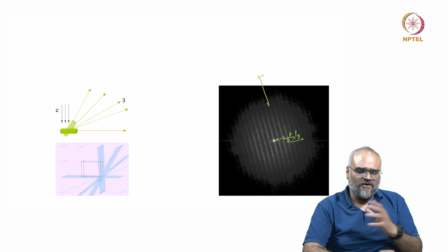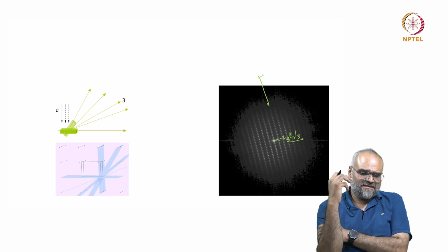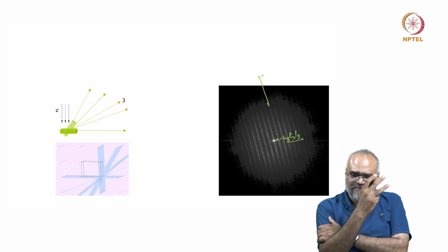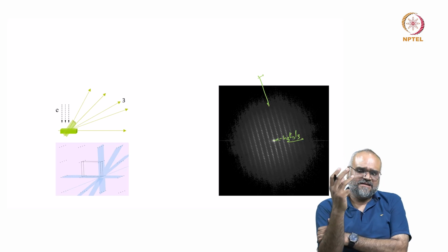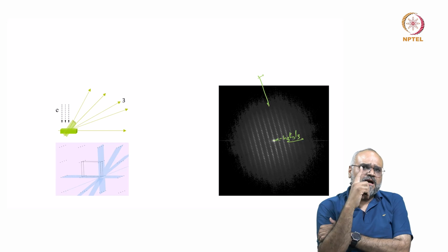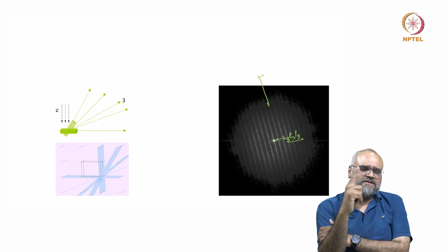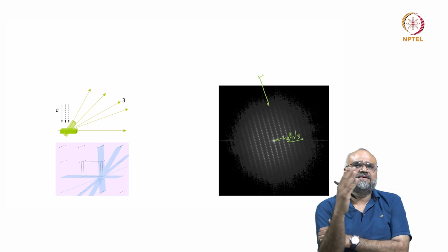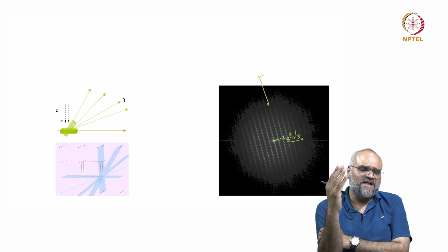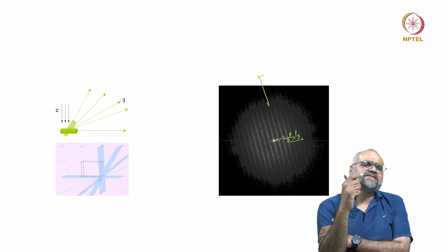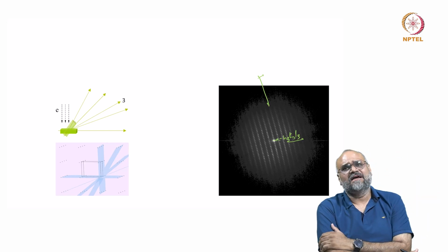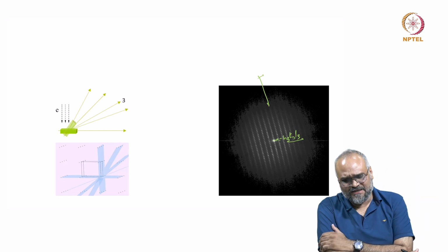I can think of this as solving the unknown three-dimensional lattice parameters with three different projections. But when I have one particular axis common for three different projected reciprocal lattice images which are diffraction patterns, I can actually solve the first level of my crystal structure problem, which is knowing the unit cell parameters.